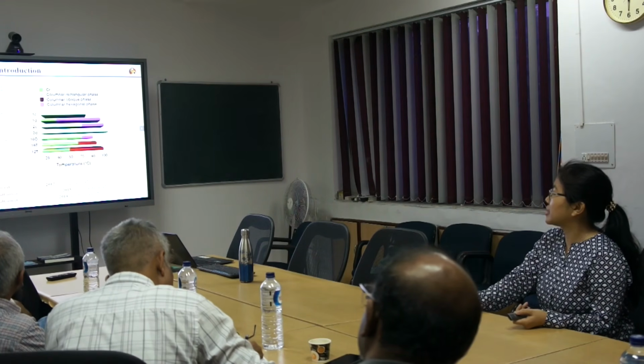In previous work from our lab, where different substituents were used, the one with tridecyloxy chains was found to have a wide mesophase range from 168 to 30 degrees Celsius.